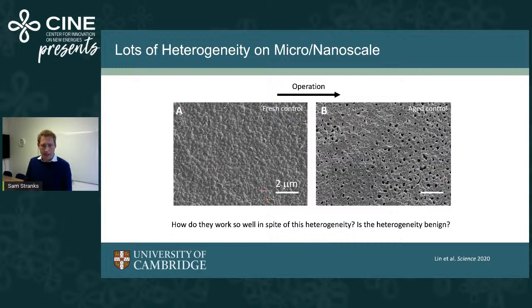One more layer to add to that is if we also think about the operation of these materials. If we operate them as solar cells for many hundreds of hours, for example, what we see is that the degradation of the absorber layer starts to happen on very small length scales. You see the formation of pinholes over time. And so again, the question is how this relates to some of this heterogeneity.